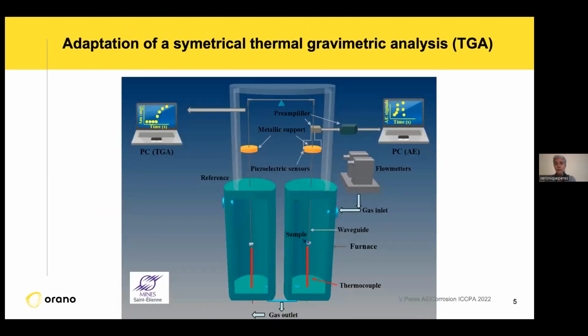So this is a drawing of the system. You can see here the 2 furnaces, the reference one where we put nothing, and the second one where we put the sample which will be submitted to corrosion. And here you have a waveguide. In the upper part of the system, you have 2 metallic supports, and on one we put a sensor, which is a piezoelectric ceramic, and preamplifiers, which permit us to record the events coming from the samples and treat the data. You also have a gas inlet here and a gas outlet at the bottom of the system.